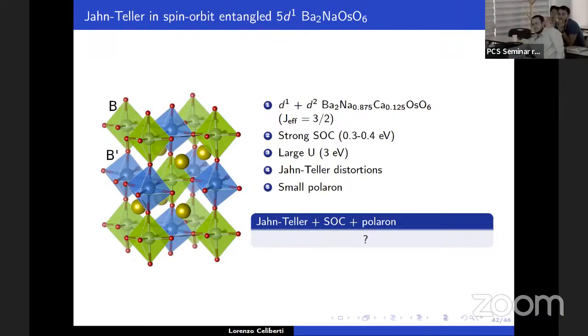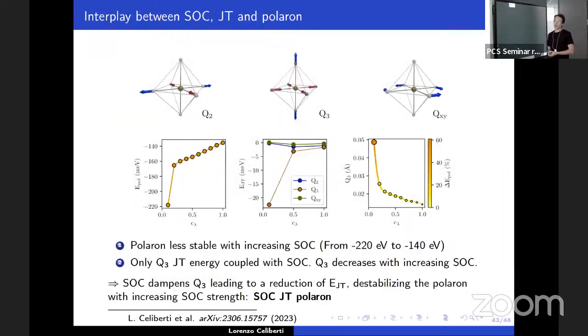So now at this point, as I told you at the beginning, this was one of the first cases with polaron material with strong spin-orbital coupling. So we wanted also to try to understand what was the role of spin-orbital coupling in this polaron formation. So what we studied is how the polaron energy changes with the strength of spin-orbital coupling, as you see in the plot on the left. And you basically observe that the polaron is less stable as you increase spin-orbital coupling. This C lambda tells you the strength of the spin-orbital coupling. One corresponds to the ab-initio value of the spin-orbital coupling term. And you see that this becomes less stable as you increase spin-orbital coupling.